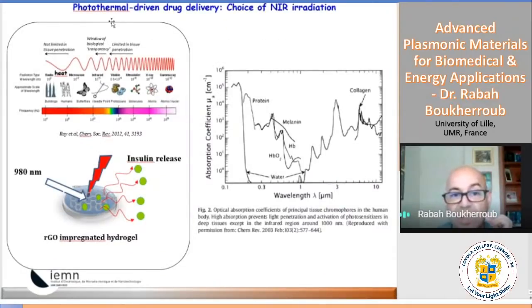Well, and we wanted to use photothermal, but in the near infrared. The reason why is that in the near infrared there's a very small window, about 980 nanometers, where nothing absorbs. Not the proteins composing the skin, nor water. It means I cannot generate any damage to the skin.